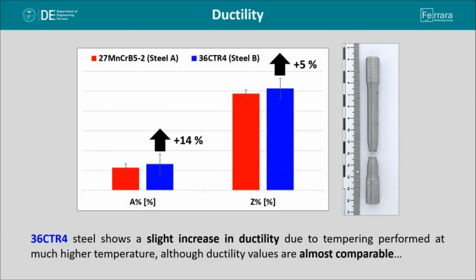In terms of ductility, steel B shows a slight increase in ductility because of tempering performed at much higher temperature, but the most important thing we can assess within the present slide is that the ductility values are comparable if we take into account both the elongation after fracture and also the reduction of area after fracture.